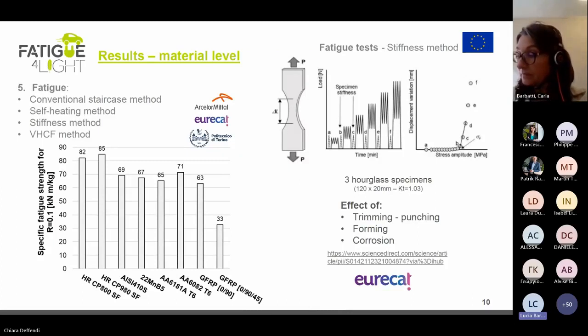Basically, we are applying blocks of 6,000 cycles of loading with increasing levels of amplitude. And after each block, we measure the stiffness of the material. So we unload the material and we measure what is the stiffness response. And when we detect a change in this stiffness is when we can say that we have located the fatigue